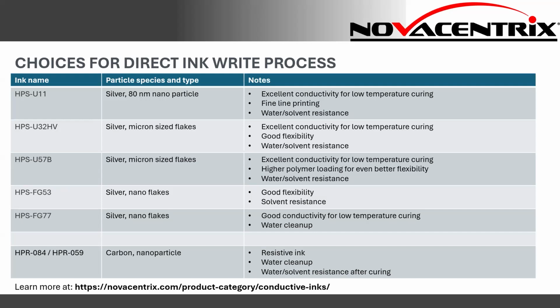If you look at some of the earlier work that we had, that was done with Voltera, we used a carbon nanoparticle based ink, and carbon is a very good choice if you're making resistive heaters and things like that. It's also water based, so it's very easy to clean up using just water, and after curing, they're very fast materials, so they are water and solvent resistant after curing.